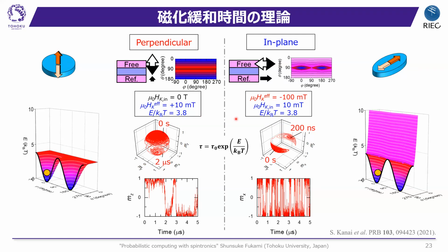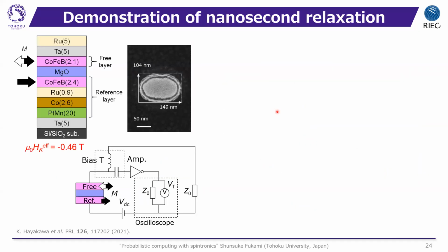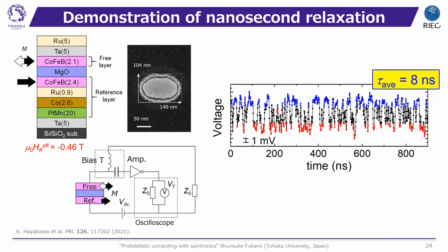So making a long story short, what we found is that the tau zero, the attempt times, are largely different between these two cases, and this attempt time can be dominated by the slope of the potential well. Because the in-plane magnet has the steep slope due to this hard axis, negative anisotropy along the out of plane, this leads to a reasonably short tau zero, and also the thermal stability factor can be reduced by reducing the in-plane anisotropies. And based on this concept, we fabricated the in-plane stochastic MTJs, and indeed, we observe very fast nanosecond fluctuations.